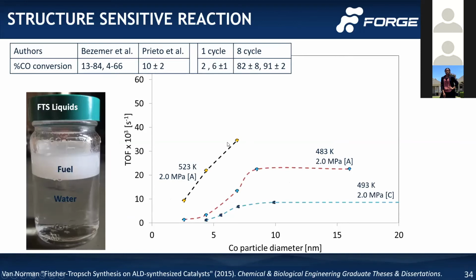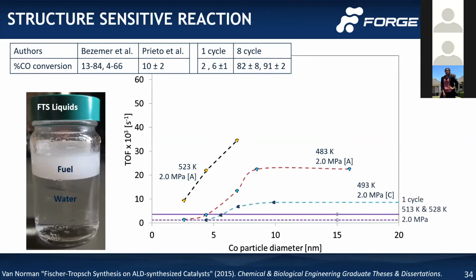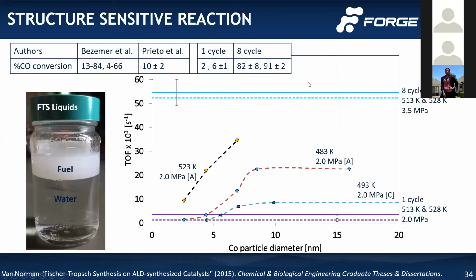So again, this is that same data. It's a structure sensitive reaction. Once you get up to 7 to 10 nanometers, the turnover frequency stabilizes. You're not using any of those other cobalt atoms that are interior to the particle. Bringing in the ALD data, the one cycle catalyst looks like very, very small nanoparticles, in fact around 1 nanometer, which is what we would expect. But if we look at the 8 cycle catalyst, with these error bars, we're much higher than any turnover frequency you would expect to see.